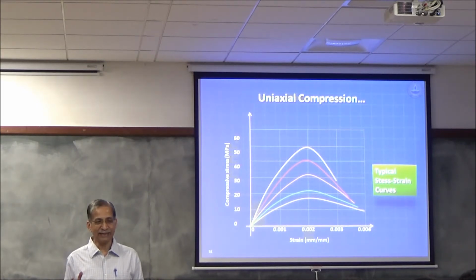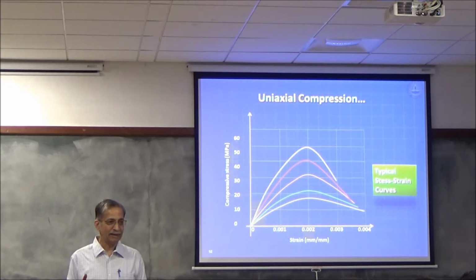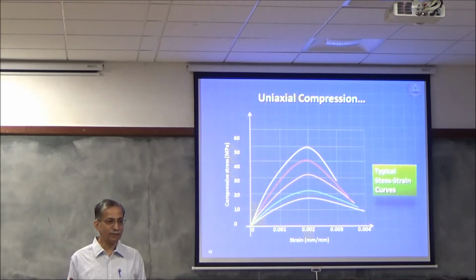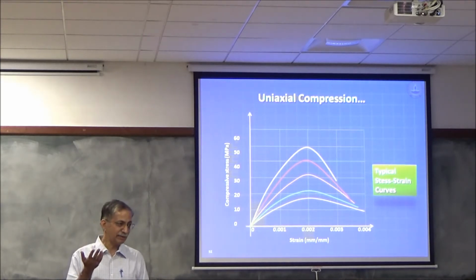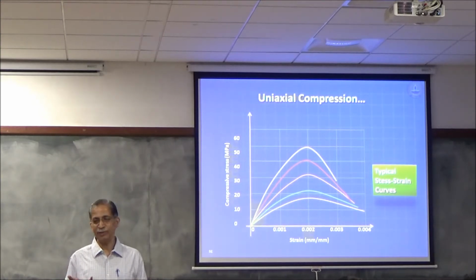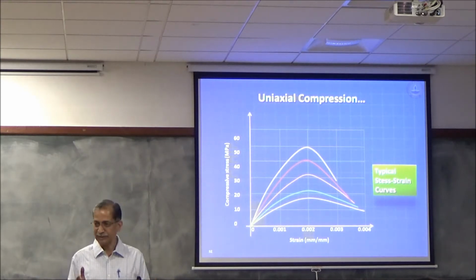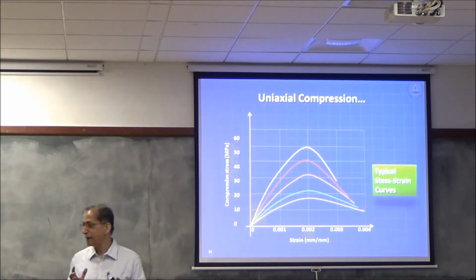It's stiffer, so it looks like it's more solid. And if it is more solid, it means the fluid part is less. So normally if you want to make a richer mix, you have to cut down the water, cut down the water cement ratio. It's a harsher mix. You'll automatically get an increase in strength. So intuitively, the primary reason is that you have less voids in the mix. The microstructure is more compact.